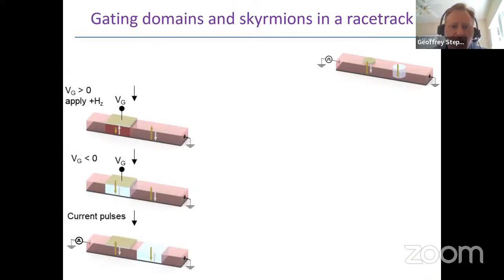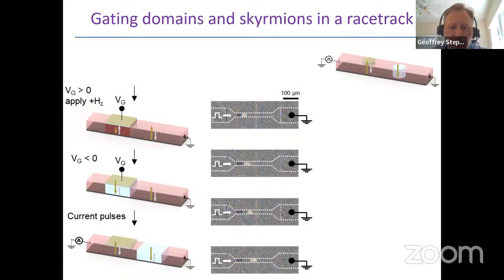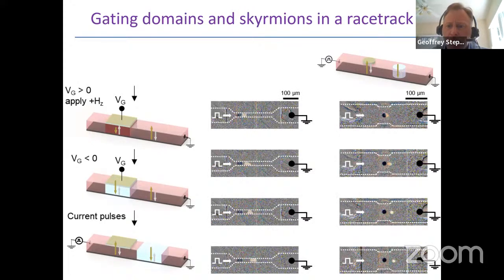We can create structures that we can locally gate, and with an appropriate field and current protocol, we can create magnetic domains, pairs of domain walls, or create magnetic skyrmions in a racetrack device, which, as I've shown you before, is the same material class that can host very small skyrmions and the same material class that can host very, very fast skyrmions. So this is a very interesting way, potentially, in which one can integrate gating into a device to allow for these kinds of localized functionalities.